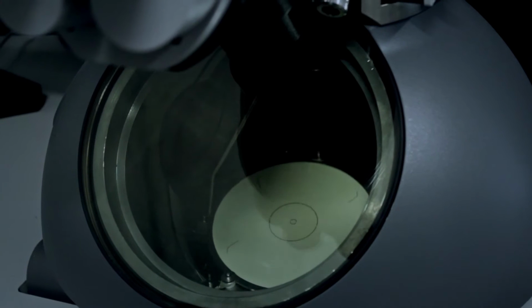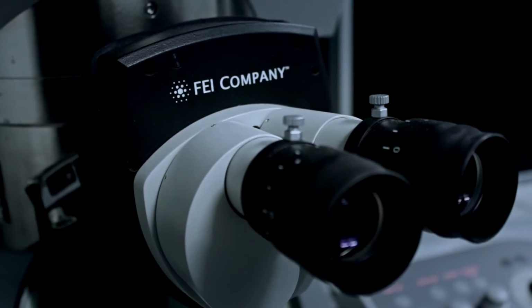What we're trying to do here is to bring together all of the different pieces of equipment to go down through the scale so that we can take the same piece of material and understand it at each level. So, for example, if you had a crack growing, that crack may be growing in a pipe or a large component. You want to understand how it moves through that component, and you may study it at the millimetre scale. We would do that with X-ray imaging, using our Nikon-based large-scale X-ray imager. We might follow that growth until a key point where we may want to understand that at the micron scale.